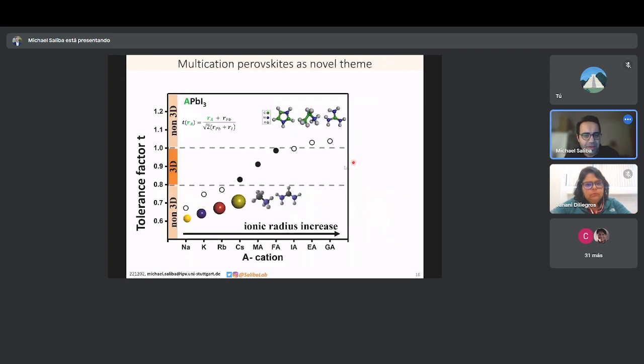So let's look at it more systematically. Here on the y-axis, you see the tolerance factor. Only 0.8 and 1.0 give a stable structure if we fix the lead and the iodine. And then on the x-axis, we have different cations and their radii. You can see here the alkali metals, they are obvious targets. Cesium, for example, is well known, methylammonium and formamidinium. These are the only ones that are suitable for this tolerance factor relationship. All the others don't fit.